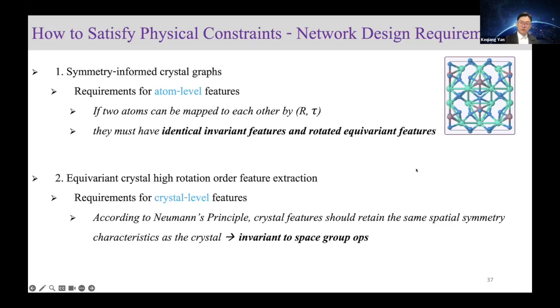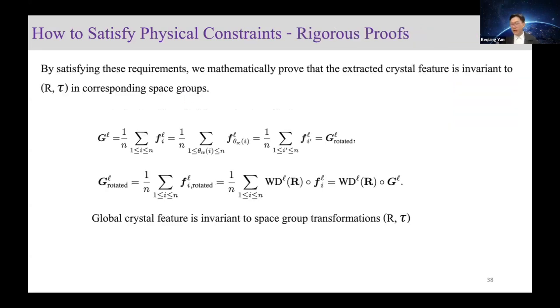And additionally, for the crystal level features, there are some requirements because, according to Neumann's principle, crystal features should retain the same spatial symmetry as the structure. If you rotate the structure, it is the same structure. Then if you rotate the representation by the same transformation, the representation should also remain the same. And by achieving these requirements at different blocks, at different levels, we mathematically prove we extract crystal features invariant to all the space group transformations.